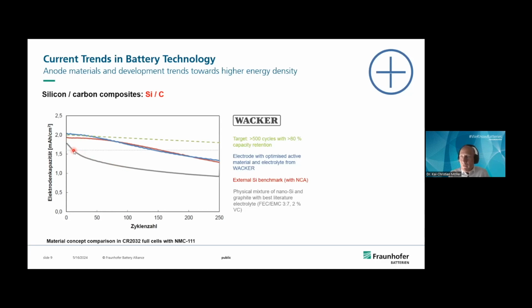But if you have an optimized material and have the nanosilicon somehow incorporated into the graphitic structure, the values are much better for the remaining capacity. So you can already reach 150 cycles, which is quite good, but not enough. A rule of thumb would be to have after 500 cycles, also somewhere here, remaining capacity of 80%. So there is still an effort to do.